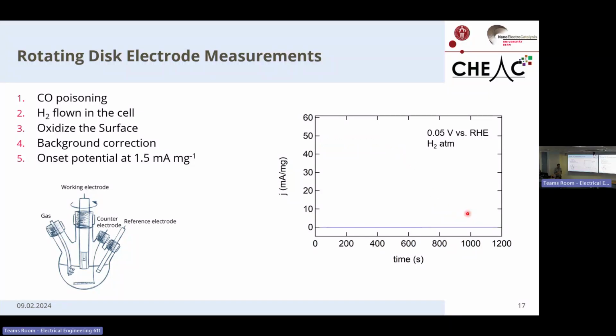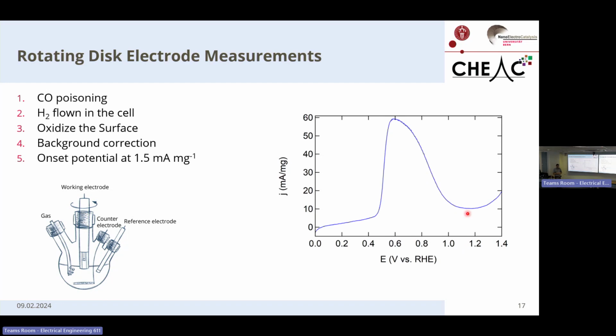After that, the CO is substituted with hydrogen, and then it is stripped by a positive sweep of the potential. So the moment CO is oxidized at the potential, you produce active sites that can perform the hydrogen oxidation reaction. So the hydrogen oxidation reaction acts as an amplifier of the moment that the CO is leaving the surface, which results in this very sharp spike in activity.